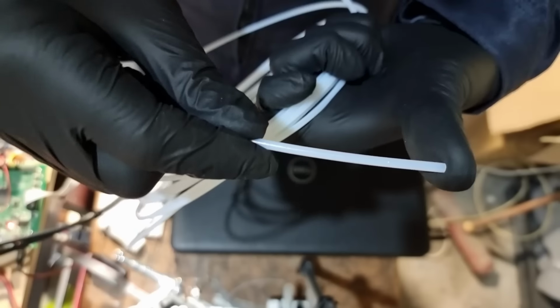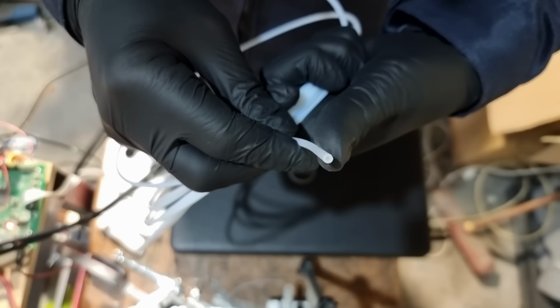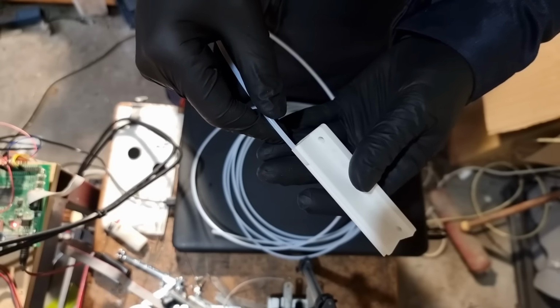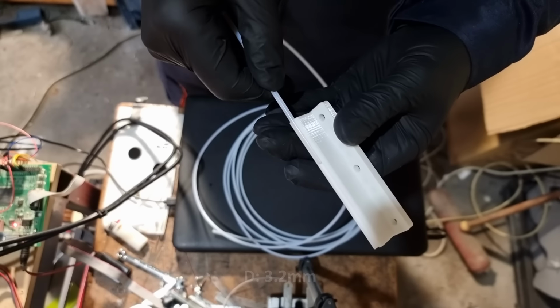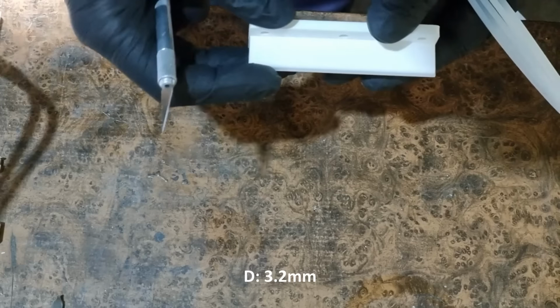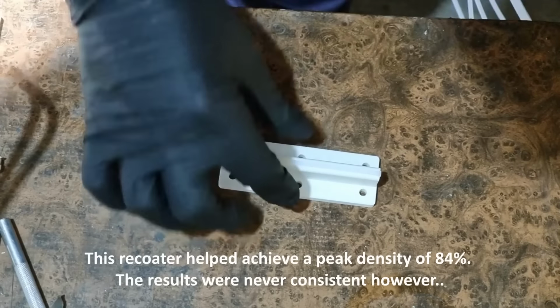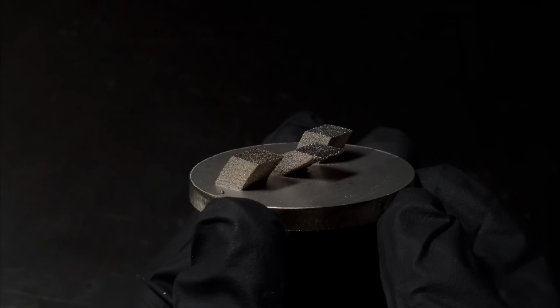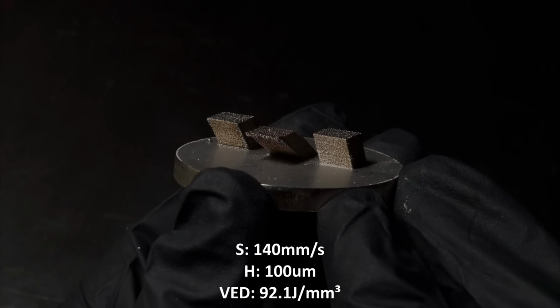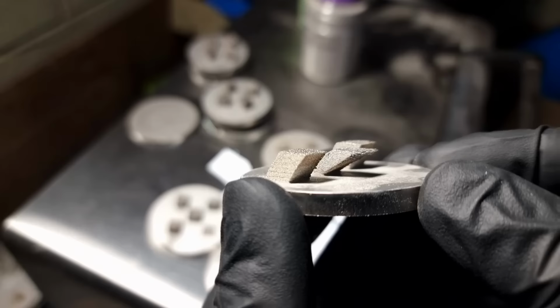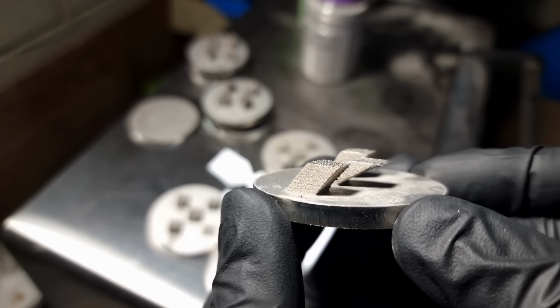The actual source of it would simply come down to the angular edges having an increased cutting effect on the recoater blade. I ended up replacing it with a rounded edge made from a harder wearing material, that being PTFE tubing. Unfortunately, I only had a smaller size on hand, but it would still address the problem whilst also slightly improving the part density. I also tried reprinting the overhangs, and these yielded pretty much the same results, but with far less interference from process failure.